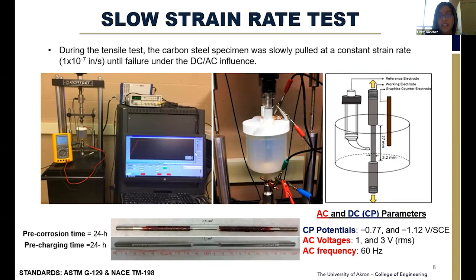So the sample is immersed in a solution that simulates the soil composition. And we have here the electrodes for the electrochemical test, a potentiostat that induces the cathodic potential, and a function generator to apply the AC voltage. These are the conditions, the parameters that I normally use: AC voltage, the cathodic potentials. The frequency is constant, 60 hertz.